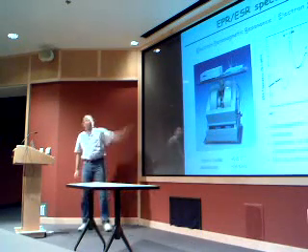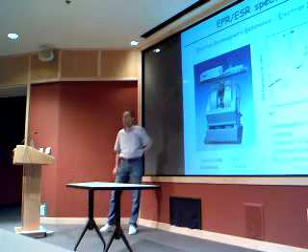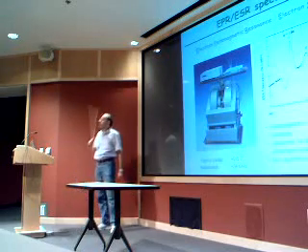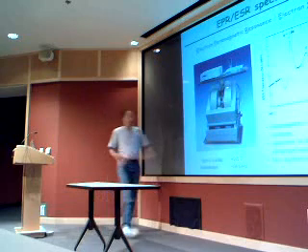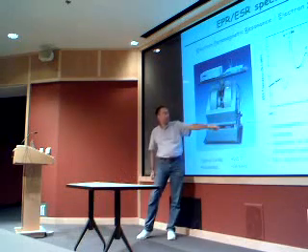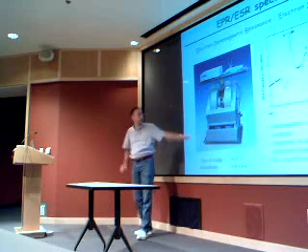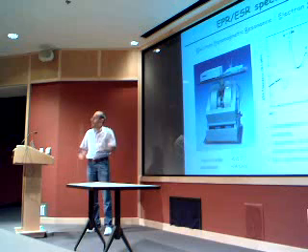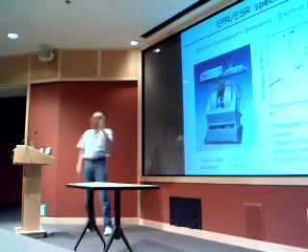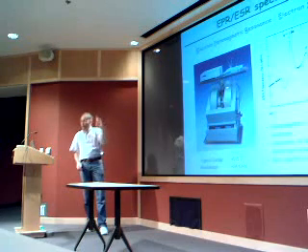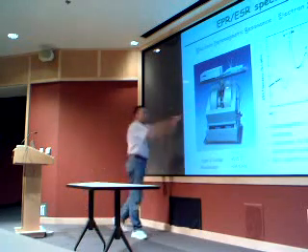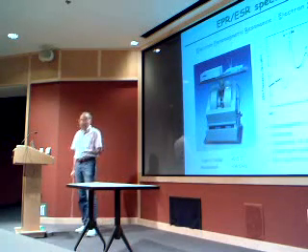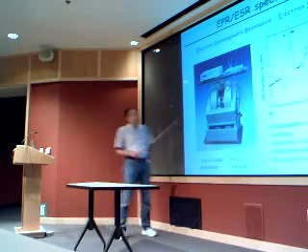And this is a typical EPR spectrum. EPR stands for electron paramagnetic resonance. Now we are not probing the resonance of a nuclear spin, but we are probing the resonance of an electron spin. It can be used to study paramagnetic defects in solids, radicals, proteins for instance, radicals in proteins or in organic molecules. By paramagnetic defects, I mean that when you have a defect in a solid which has one unpaired spin, this unpaired spin can be flipped up and down, and the EPR basically measures this. I remind you that radicals are also molecules with unpaired spins. Those are basically the same.